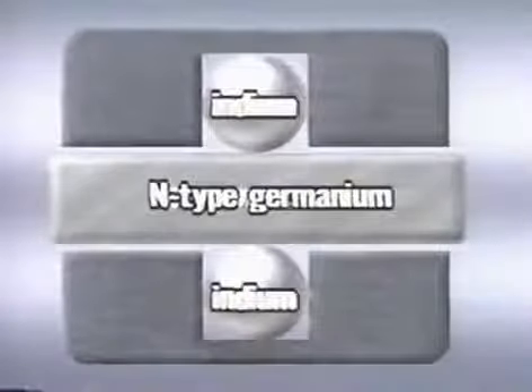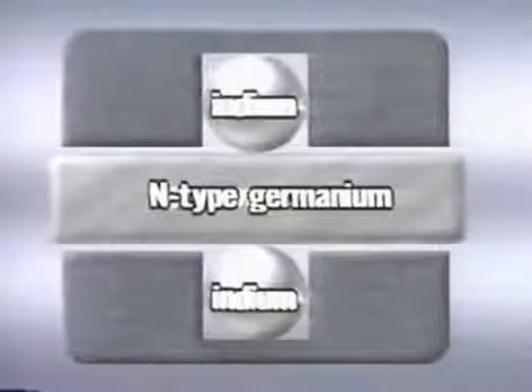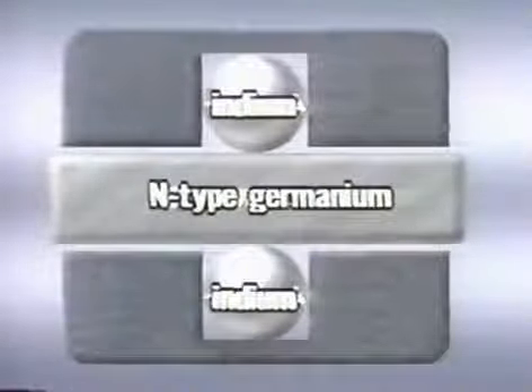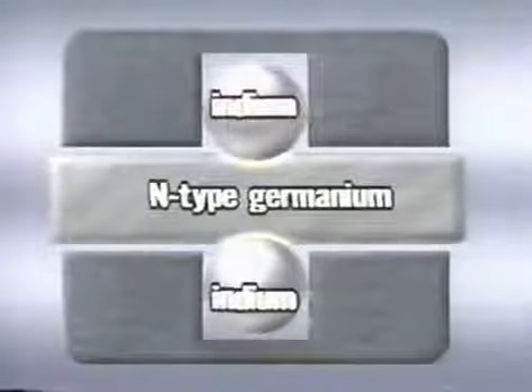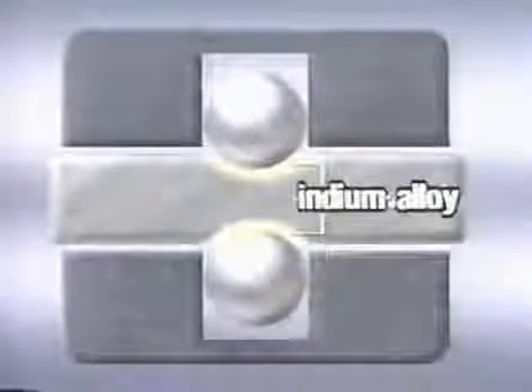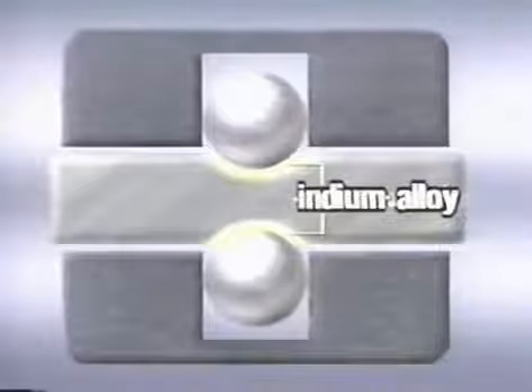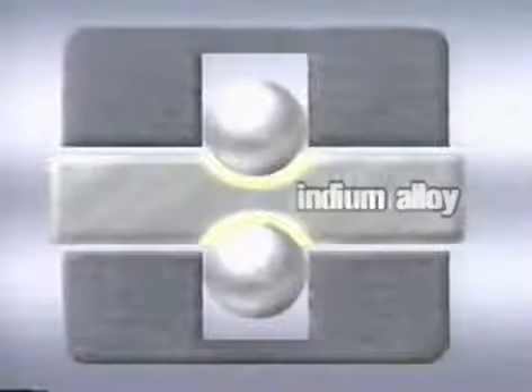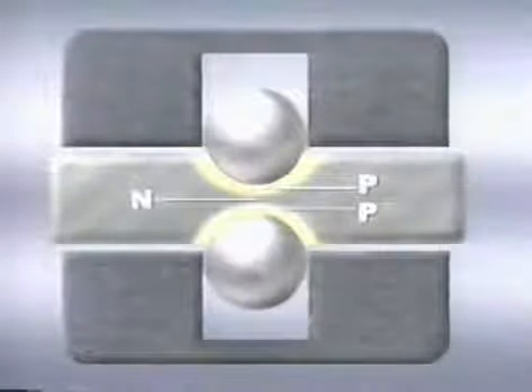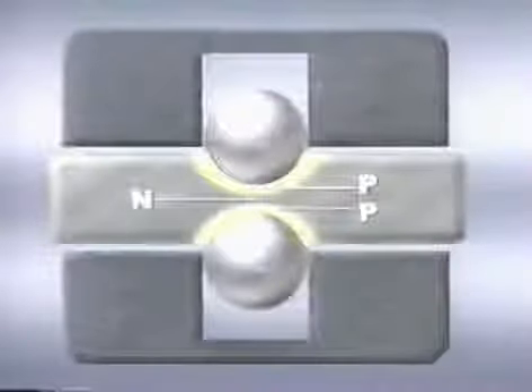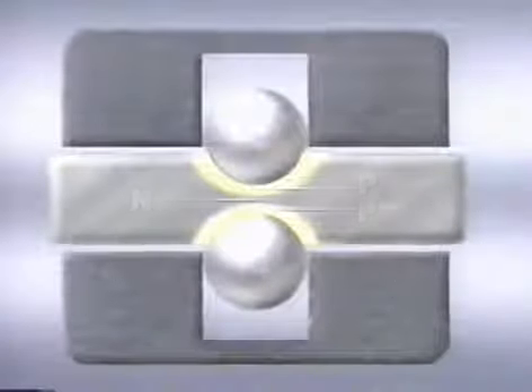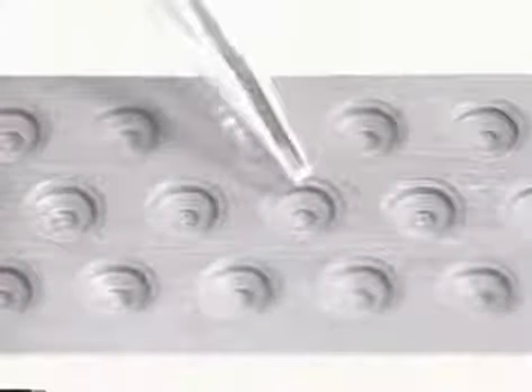At about the same time, another technology, the alloy transistor, appeared. Both sides of the N-type germanium are sandwiched between particles of the P-type material, indium, and then inserted in a furnace. The indium melts into the inside from both sides of the germanium, forming an alloy and creating a P-type layer. Since the body portion remaining in the very center is N-type, the crystals form a PNP sandwich.